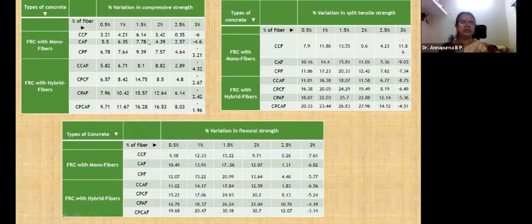Okay, and this is the percentage variation. Let me show you that the compressive strength increase is all marginal. The percentage increase in compressive strength at 1.5%, maximum, was 6.1 and 7.78. With plastic fiber, it's 9.39. That is why I told you that with the presence of plastic fiber, the compressive strength is higher compared to coir and areca. With plastic with coir or areca, it is 14.75. With the combination of all three, it is showing 16.28.